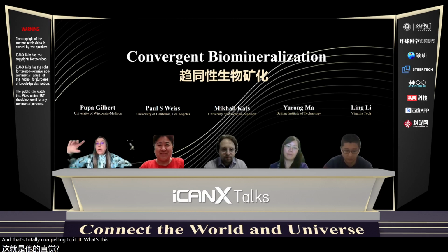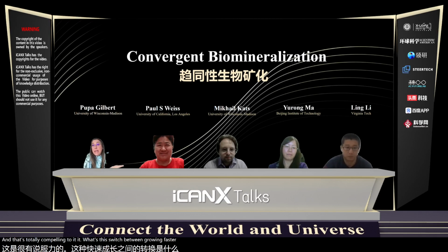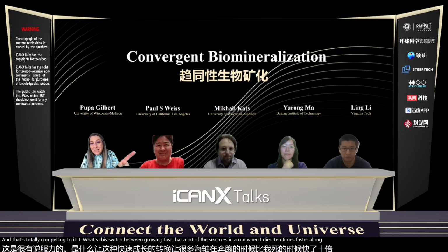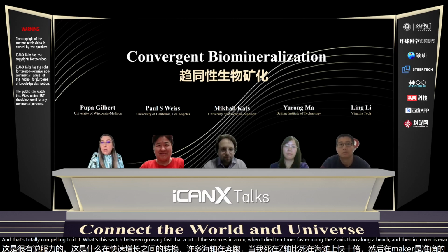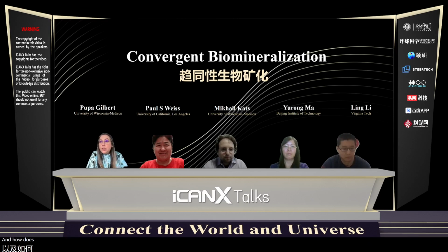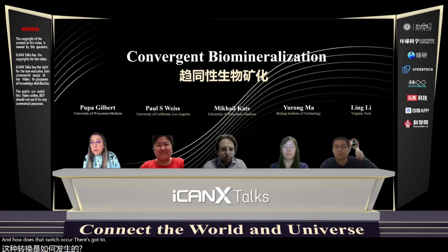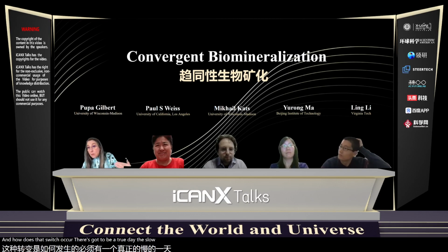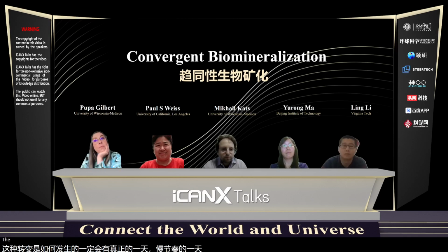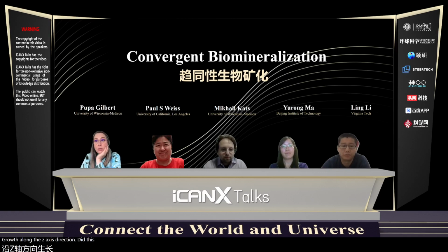What's this switch between growing faster along the C-axis? Aragonite does grow 10 times faster along the C-axis than along A and B. And then in nacre it's exactly the opposite. And how does that switch occur? There's got to be a protein that slows down the growth along the C-axis direction that does not slow it down along A and B.